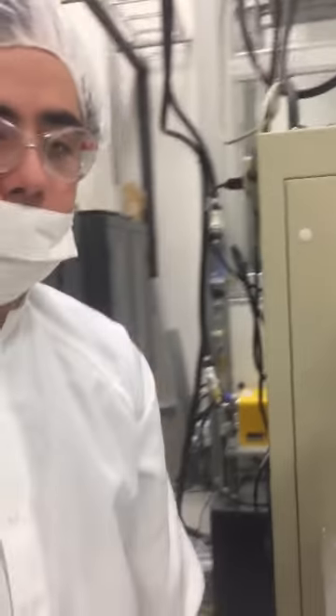So what we have is a 400 micron, or 0.4 millimeter, fused silica fiber. We have four of these that suspend the 40 kilogram optics. If we look over here, we have the mockup of our 40 kilogram test mass. The mirror — in the real thing, this is a fused silica mirror which is 40 kilograms. You can actually see the fibers at the site. These are 400 microns in diameter, all holding 40 kilograms — really, really thin but extremely strong.